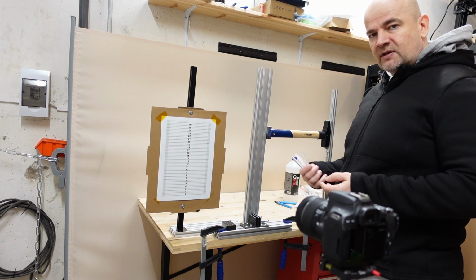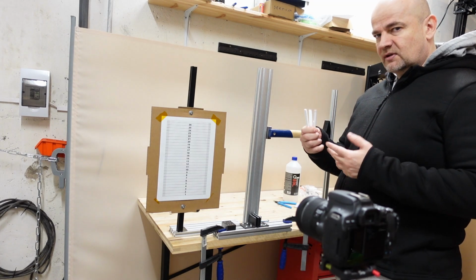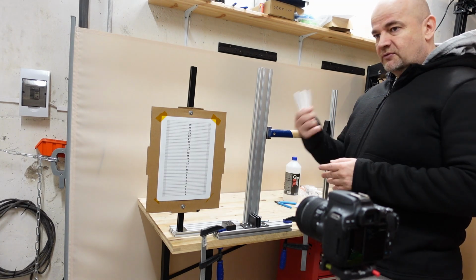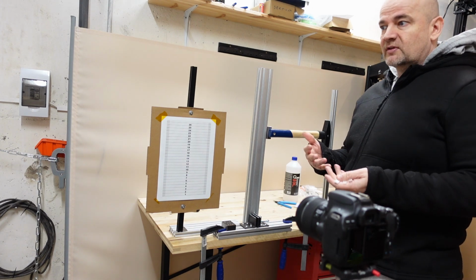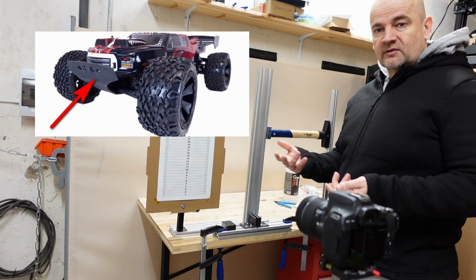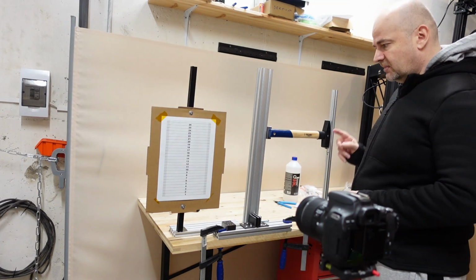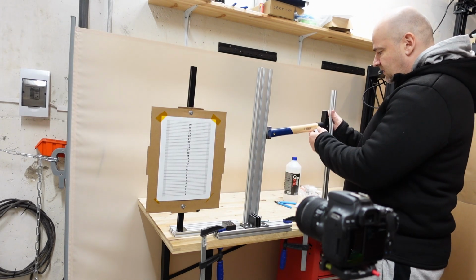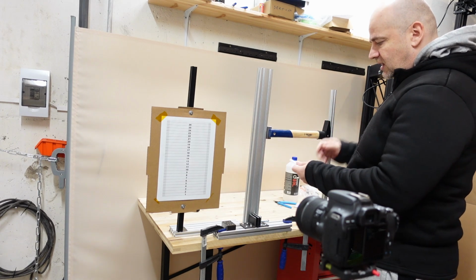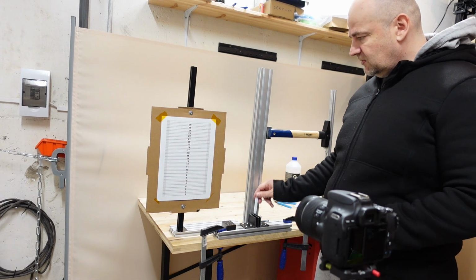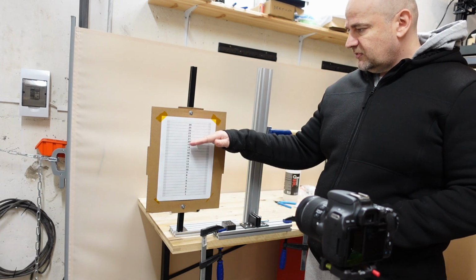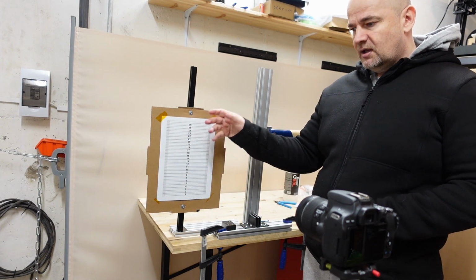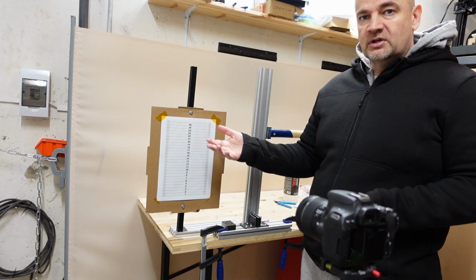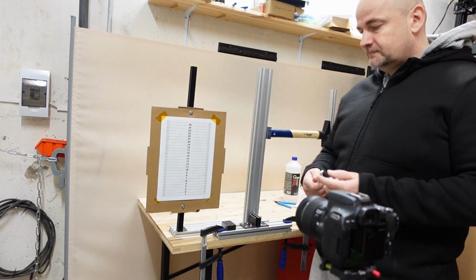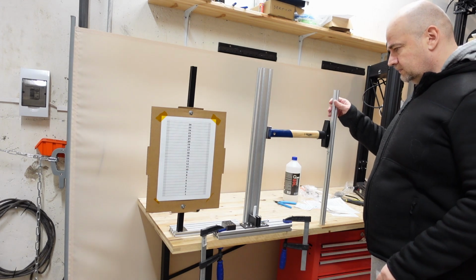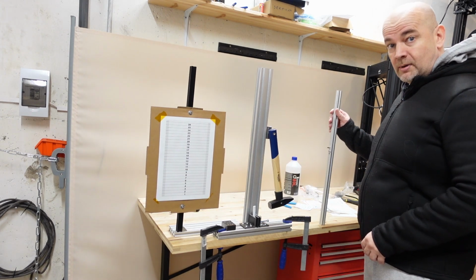With this Izod impact test I can see which of the 3 materials is more brittle. And actually the winner in this test is a good choice, for example, for bumpers on an RC car or something like that. So I have here a half kilogram hammer, and it will swing to the other side. That will be the 0 position. And after I place the test specimen here, it will break it and swing to the lower position, and from the difference in height I can know how much energy is used to break this test specimen. ABS. Oops.